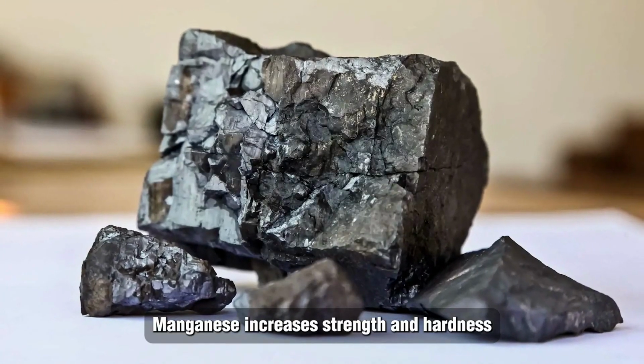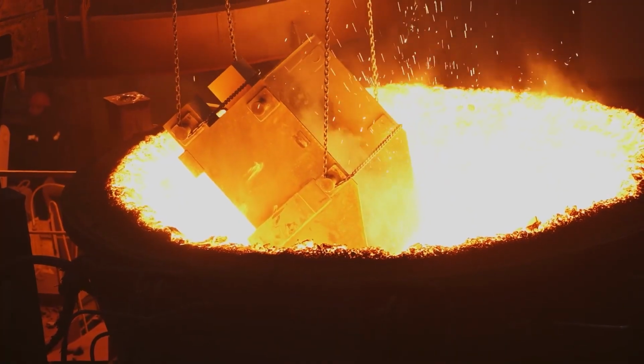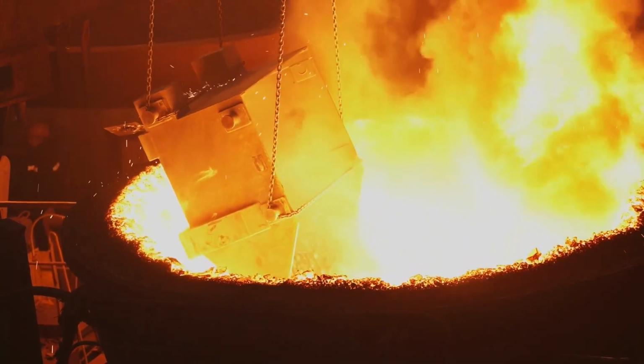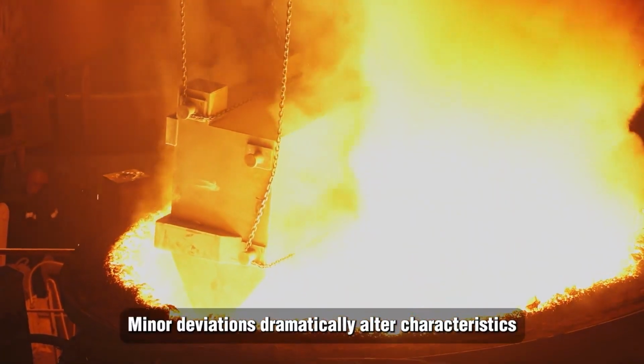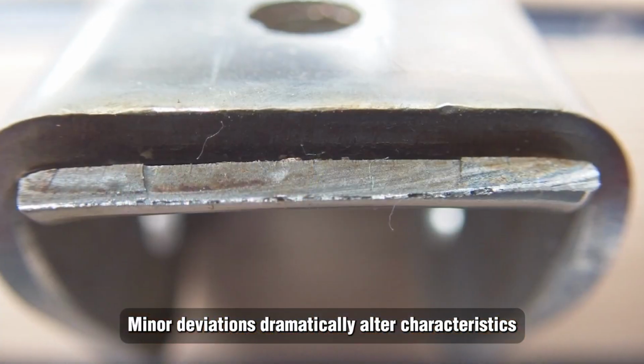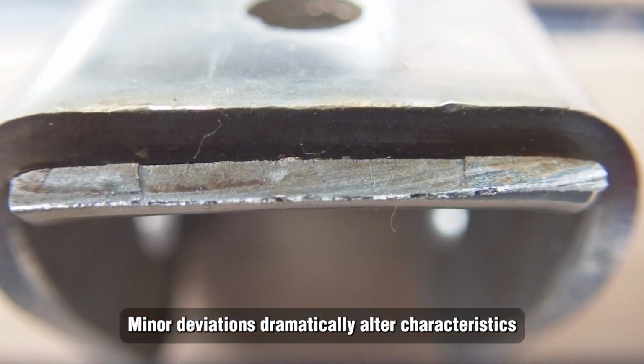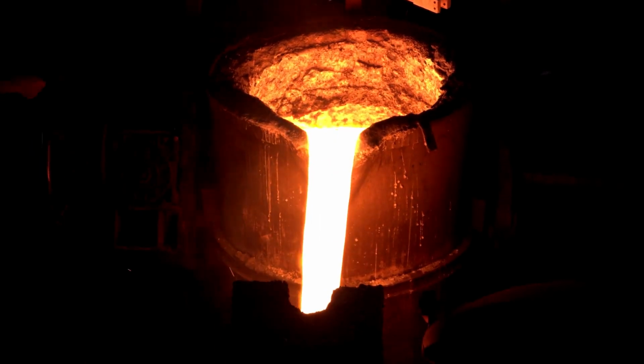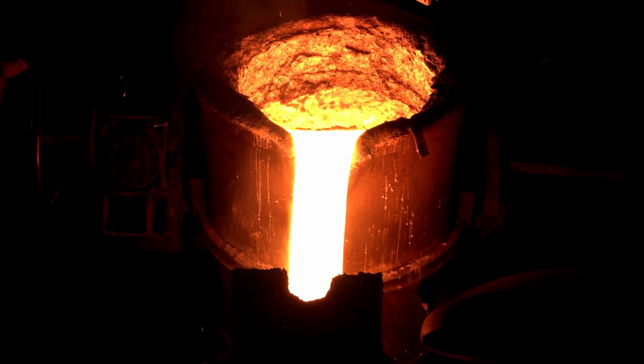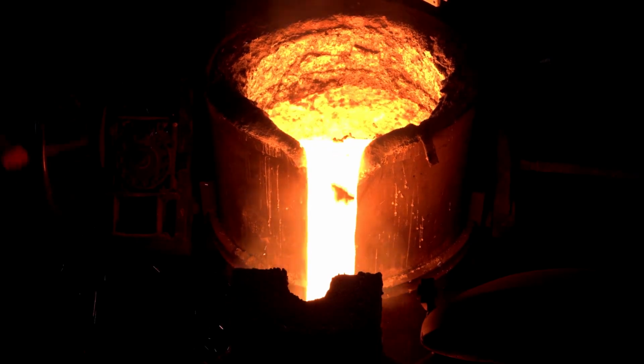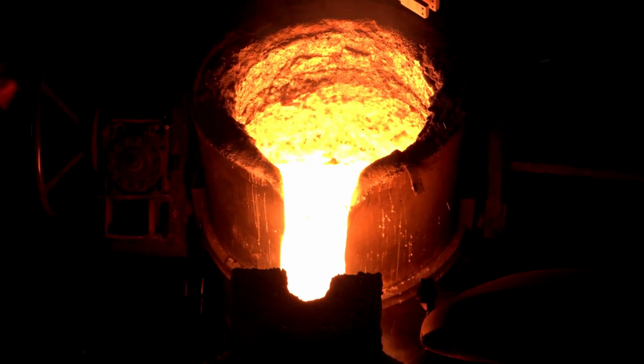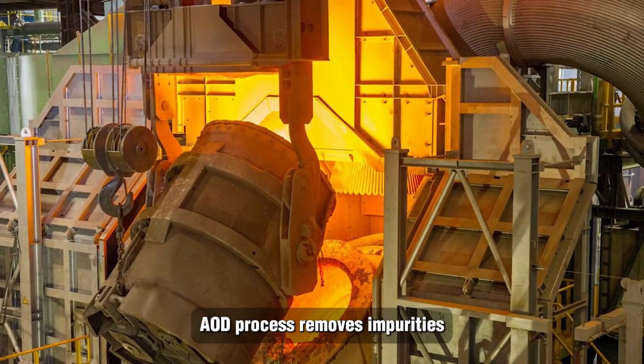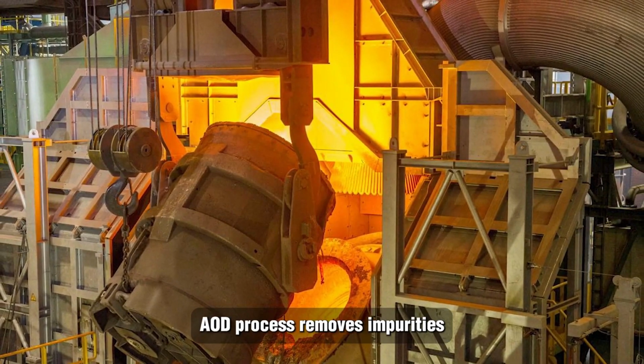Nickel adds extra corrosion resistance and gives the surface a brighter, more polished look. Molybdenum strengthens resistance against pitting and crevice corrosion, especially valuable in harsh, high-chloride environments like the open ocean. And manganese boosts overall strength and hardness. Every one of these additions gets measured with extreme precision, because even the smallest miscalculation can completely change how the final steel performs.